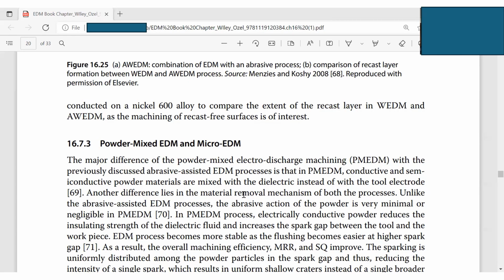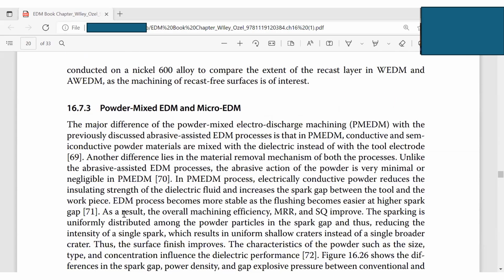But here, we just add some abrasive powders. Definitely, this is very minimal and negligible. So in this new type, electrically conductive powder reduces the insulating strength of the dielectric fluid and increases the spark gap between the tool and the workpiece. The EDM process becomes more stable as the flushing becomes easier at a higher spark gap. As a result, the overall machining efficiency, MRR, and SQ are improved.